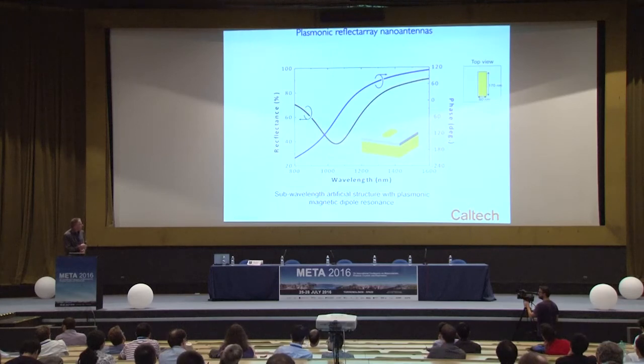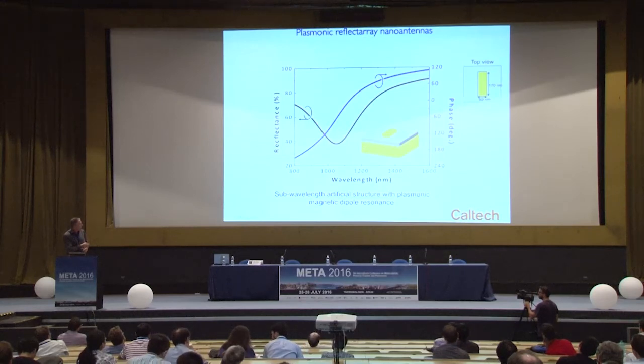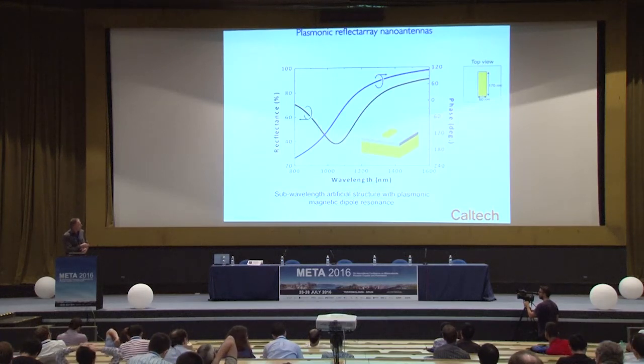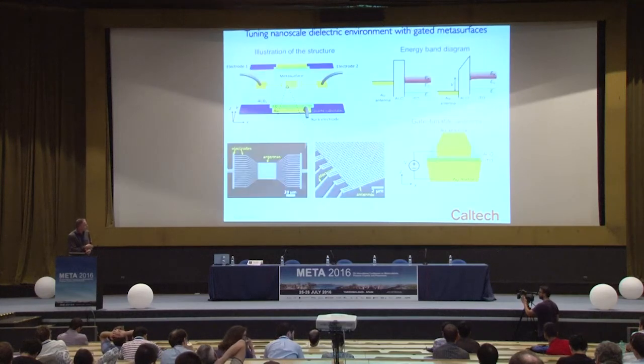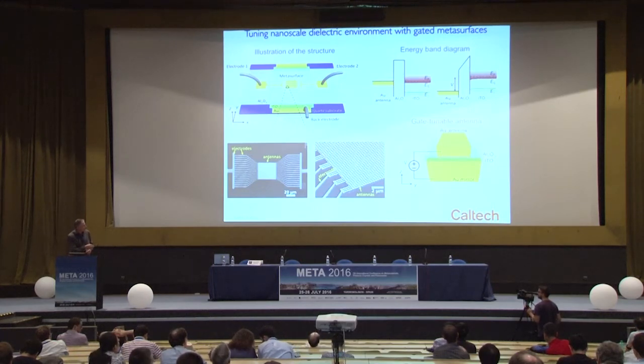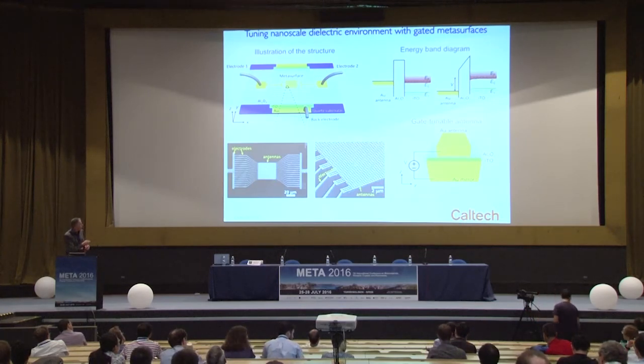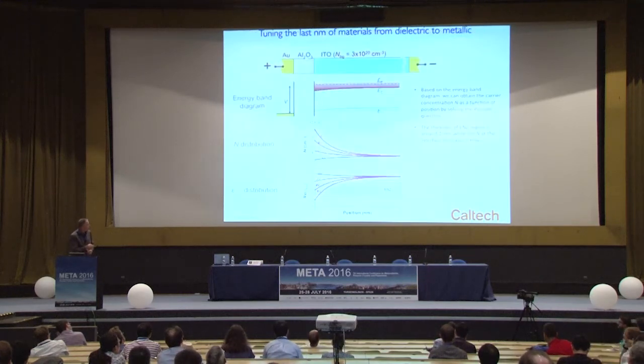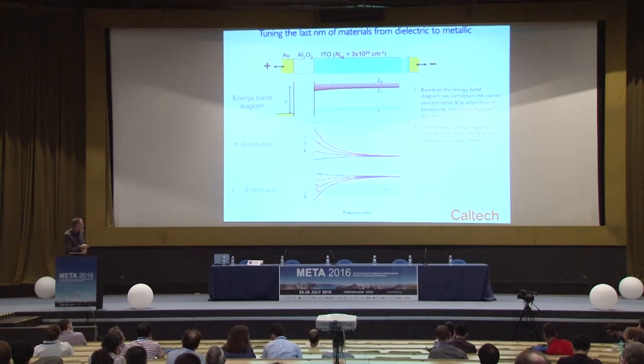So we can now fashion a reflect array antenna whose magnetic dipole response has this characteristic reflectance dip and phase change. Normally in a passive reflect array antenna, there's a dielectric gap between the patch and the ground plane. What we're going to do now is to interpose and add this tunable dielectric material, the tunable conducting oxide, in which the patch antenna itself forms the gate to tune the carrier density and the permittivity of the indium tin oxide and change its phase and amplitude response. Here's an array of antennas that are all electrically connected to form a tunable metasurface. Essentially, what we're doing is changing the complex permittivity within an extremely small region underneath the patch antenna gate, in the range of 1 to 2 nanometers.